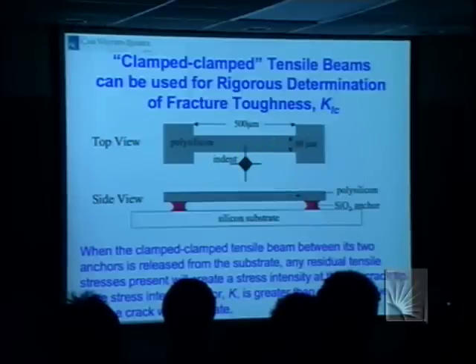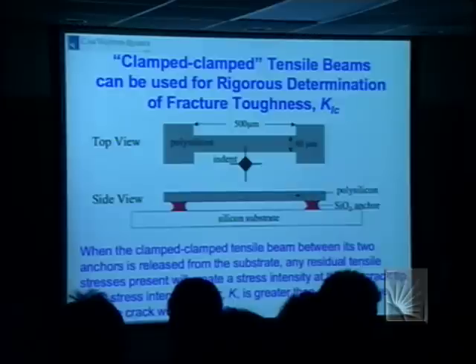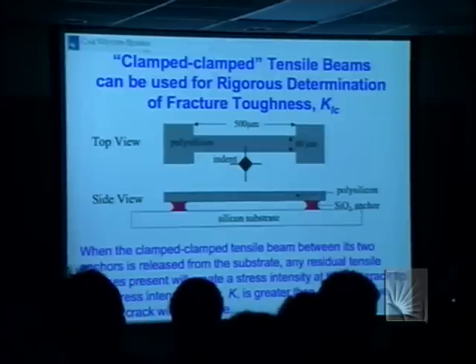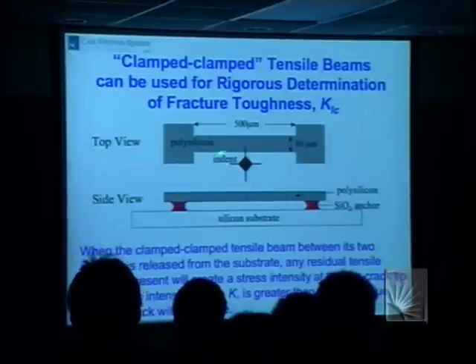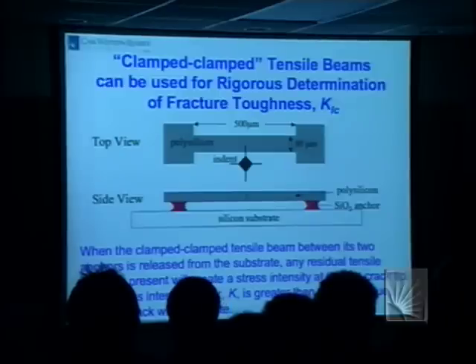It's actually very hard in mechanics to do fixed grip testing. It's very easy to calculate stresses and other aspects of mechanics using fixed grip conditions, but it's hard to achieve them in practice. In this MEMS case, this is a perfect example of a fixed grips fracture mechanics specimen. And so you can calculate what the stress intensity factor K1 is in this device, and then look to see which device has failed upon release and which didn't, and therefore you get this critical value of K1C.